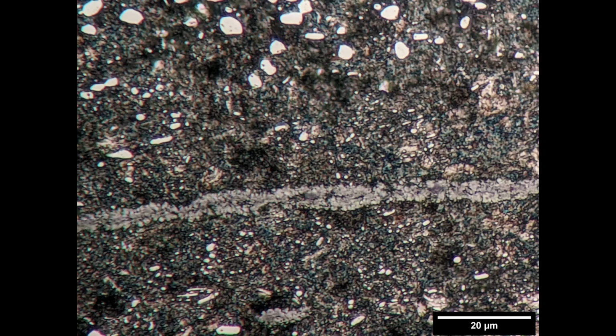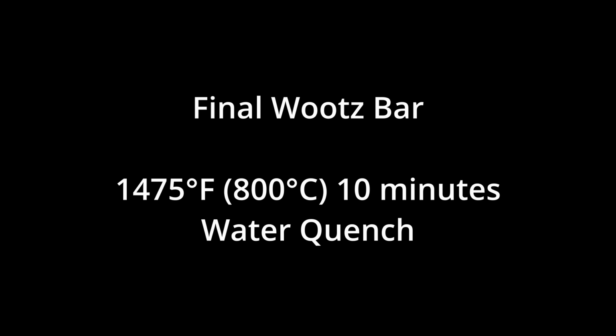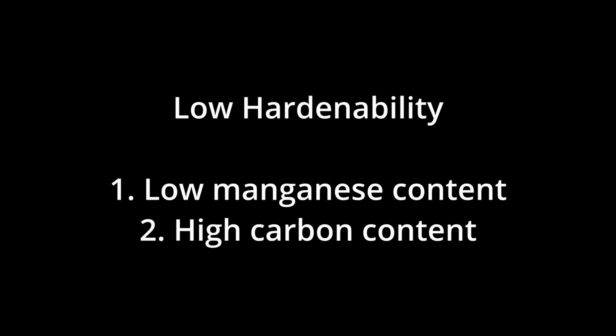We need all martensite. So eventually I learned that I had to quench in water. So through trial and error, we learned it had to be water. It's a very low hardenability steel. And that is for two reasons. One, the low manganese content that we mentioned before, and also the high carbon content. So with high carbon, the driving force, or how much the steel wants to form pearlite, is higher. So pearlite is a high carbon phase. It's alternating bands of ferrite and carbide. The more carbon you have, the more the steel wants to form carbides as it cools down. So with the very high carbon and the low manganese, the hardenability is low, and we needed a water quench.